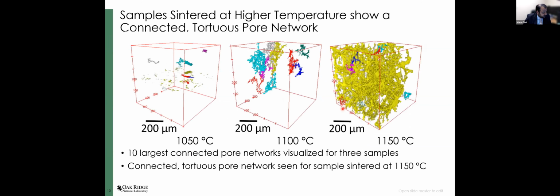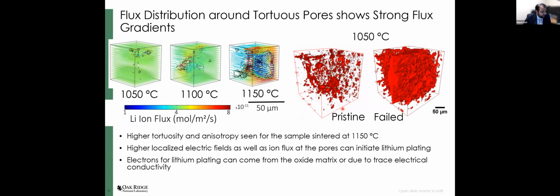And what we did was potentially one of the first synchrotron tomography experiments with solid electrolytes. And what we were able to show was that the sample sintered at a higher temperature led to a more connected, tortuous pore network that eventually led to an accelerated failure in these systems. So we did some three-dimensional modeling based on our experimental data, and we could see that the field lines across these tortuous domains were much more convoluted, and there were much stronger gradients around this that could lead to potential lithium deposition in the bulk at these higher sintering temperatures.